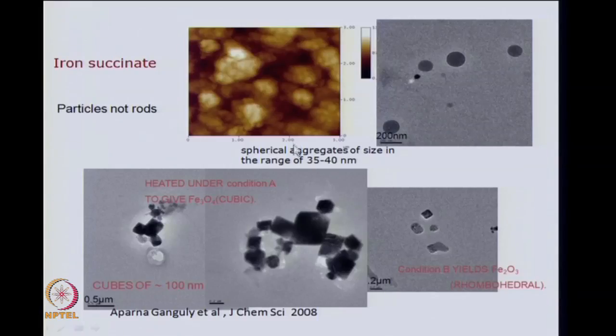You can choose, instead of oxalate, succinate, and then what we find is we do not get the rods, we are getting particles. So, the anion is also important. In all the earlier cases, we chose oxalates as the anion, and we got rods in the presence of CTAB. Here we see, although we have chosen CTAB as the surfactant, everything else is the same, except we have changed the oxalate to succinate, we get particles and not rods. So, that means the ligand is also one of the important parameters for the formation of anisotropic structures.